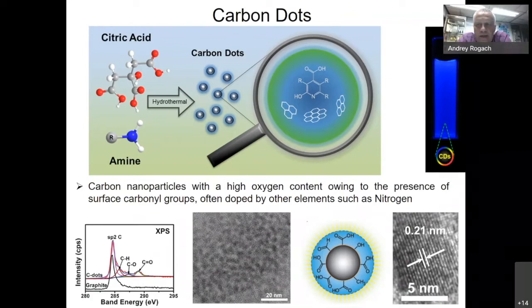And in order to make these materials emit light, we actually need to dope them. So normally we pick nitrogen, can also be sulfur or boron, to dope these carbon dots, and then they can emit light. And fortunately enough, the way we make them is pretty simple, so we can take very cheap and available precursors, like this very classical combination. Citric acid is for carbon here, and amine, short chain amine, is for nitrogen. It's a doping source, right? And then we put them into an autoclave, into aqueous solution or some organic solvents. We heat them up, and at temperatures like 200 to 300 degrees centigrade, roughly, we will carbonize these precursors, and then we make carbon dots.